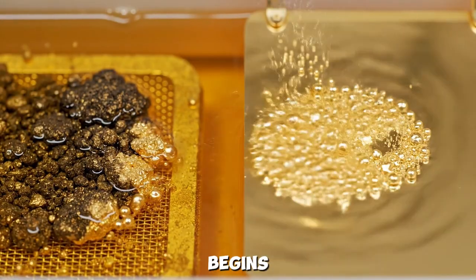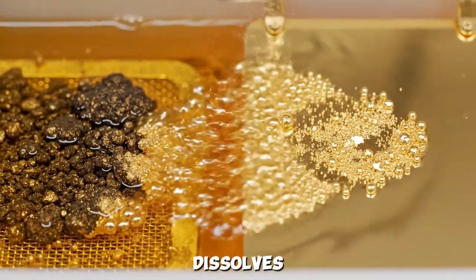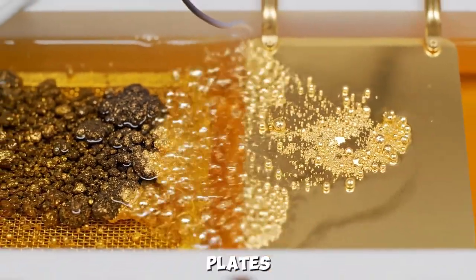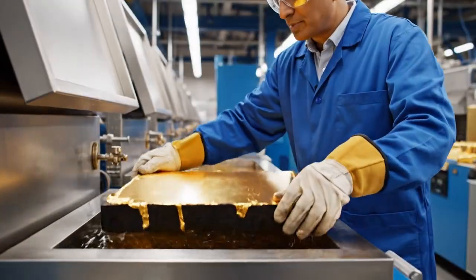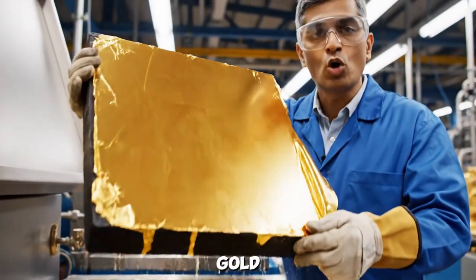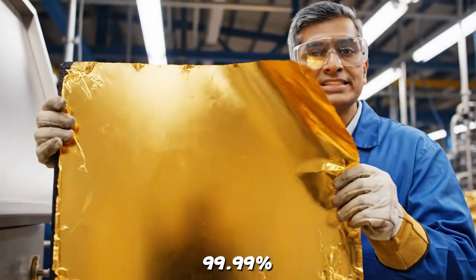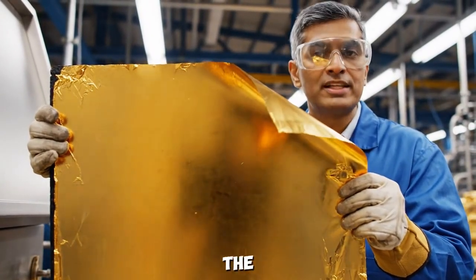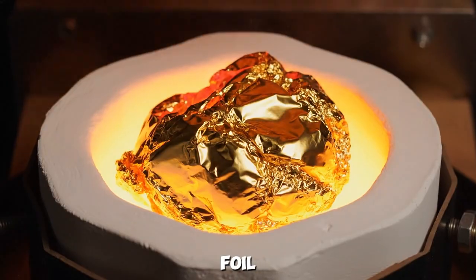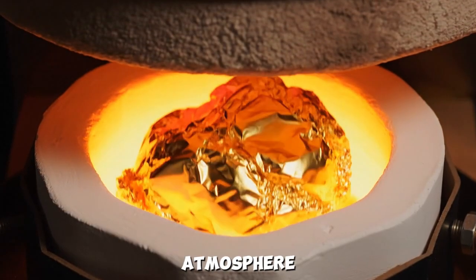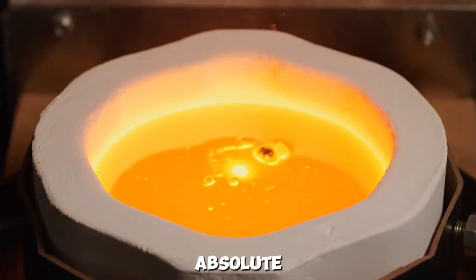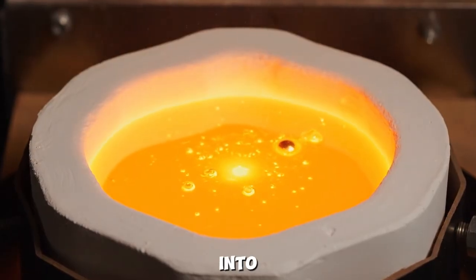Electrolytic refining begins. An electrical current dissolves the gold anodes and plates 99.9% pure gold onto the cathode. The pure gold is harvested. This foil is 99.99% pure, the international standard. The pure gold foil is melted under an inert atmosphere. This final melt ensures absolute purity before the gold is cast into its market form.